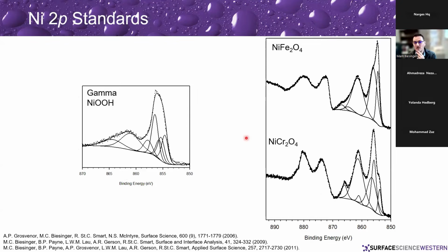If we look at other systems, we've got nickel ferrite, nickel chromite, again, very different looking spectra. So it's the spectral shape as well as the positioning that gives you all this information. If you think about what the NIST database is telling you, it's giving you a single peak position, but that doesn't tell a story really at all. It's the shapes of these things that are telling a story. And over here, we have a nickel 3 species that will again have its own unique peak shapes and modeling.